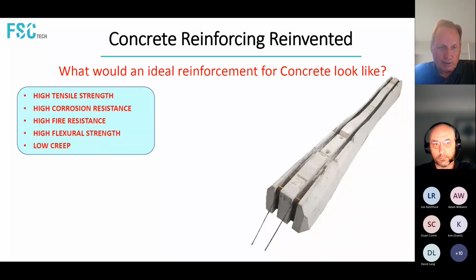One of the things with steel is that in buildings, especially, it has to be insulated because it loses its strength rapidly once you hit about 400 degrees C. So in a building fire, you don't want suddenly the steel reinforcement to start getting so weak you have progressive collapse. You'd really like to have some high flexural strength. You'd want low creep.